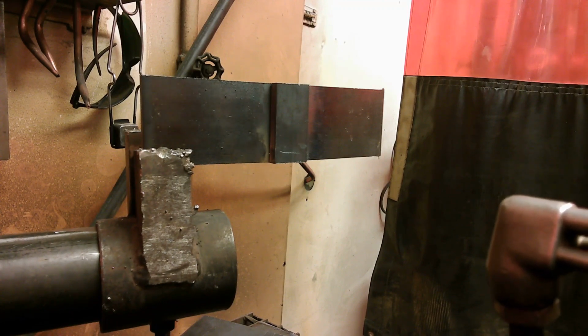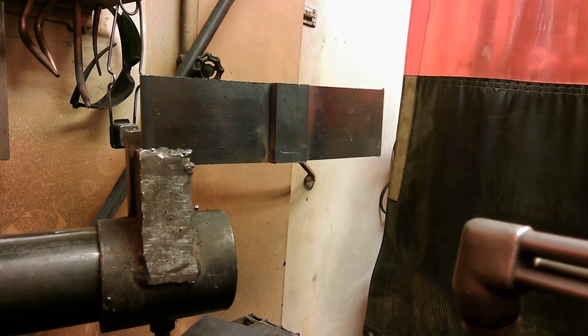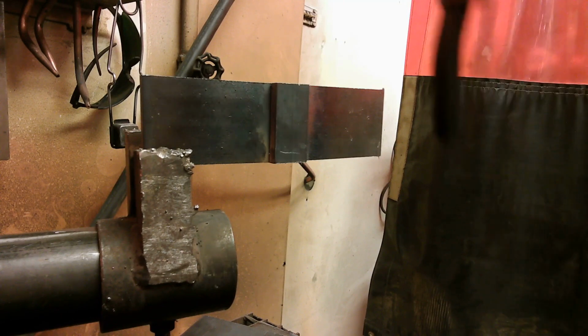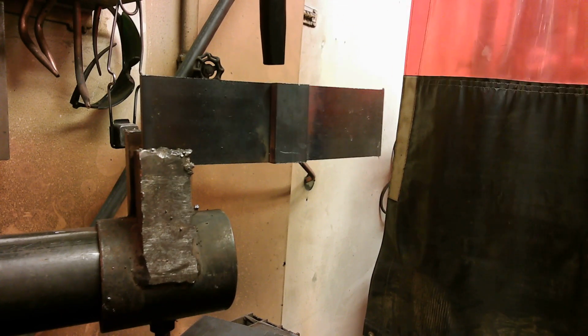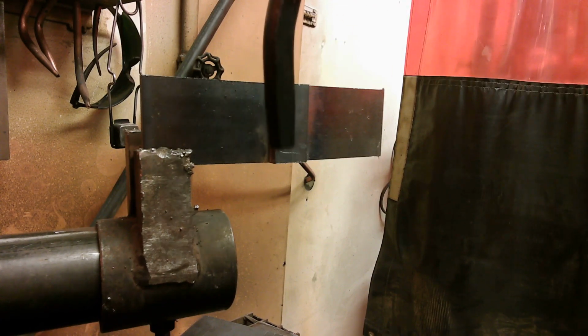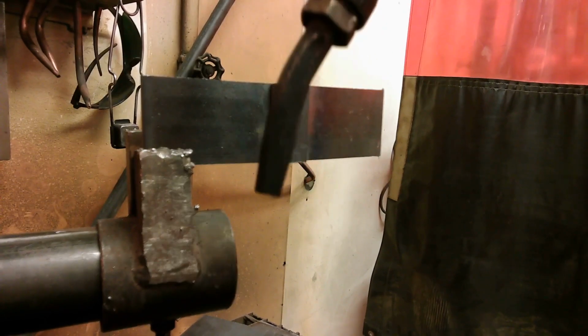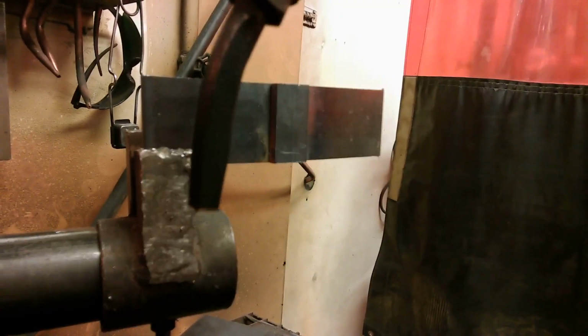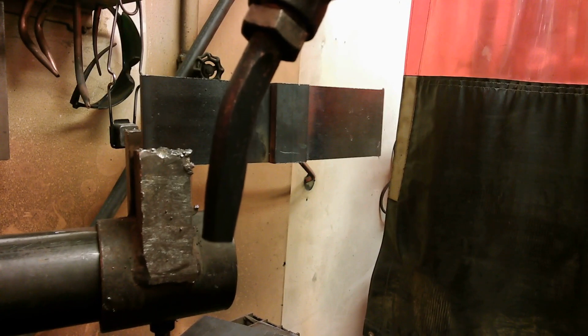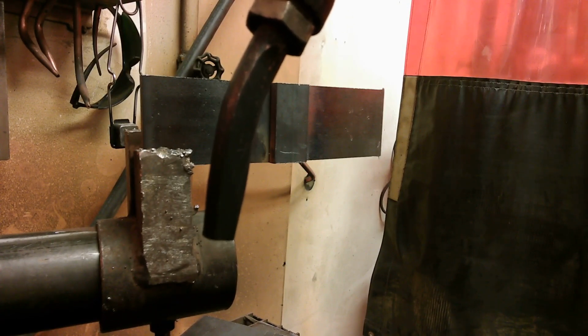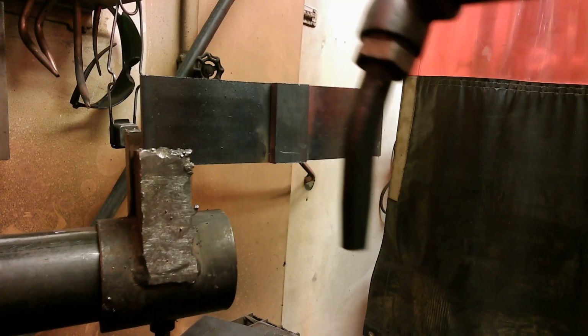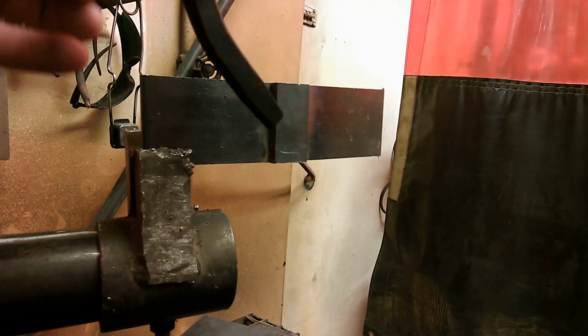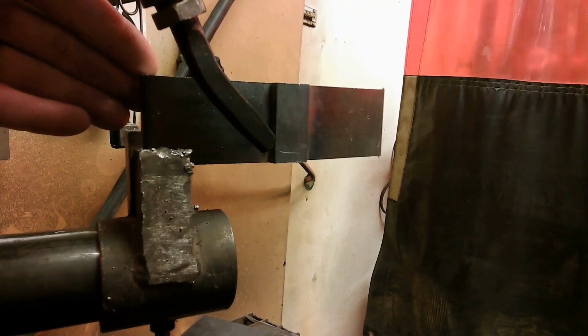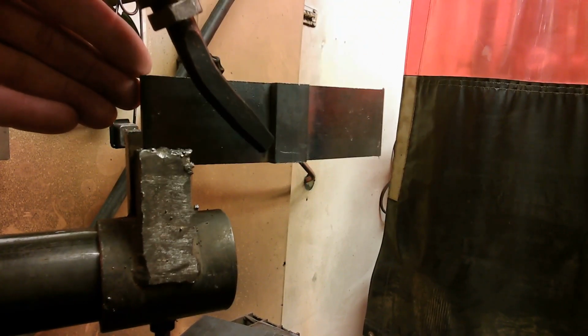It just doesn't show up real well. But I'm going to show you how I do that. Instead of just preheating at the top of this corner, it's a pretty thick piece. I'm set up with this big gouging tip. I'm running about 60 psi on my oxygen and about 4.5 or 5 on my acetylene. Since that is a pretty thick piece, I'm going to actually start down here and preheat at the bottom.